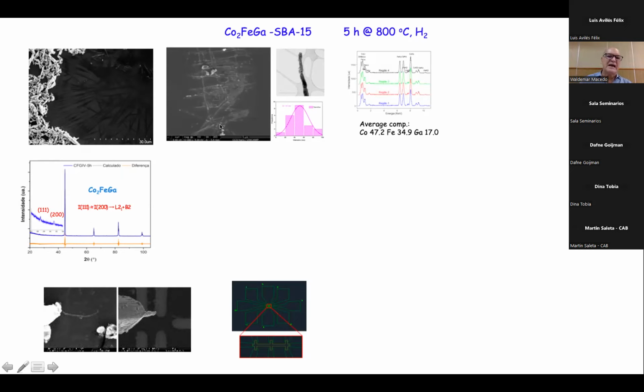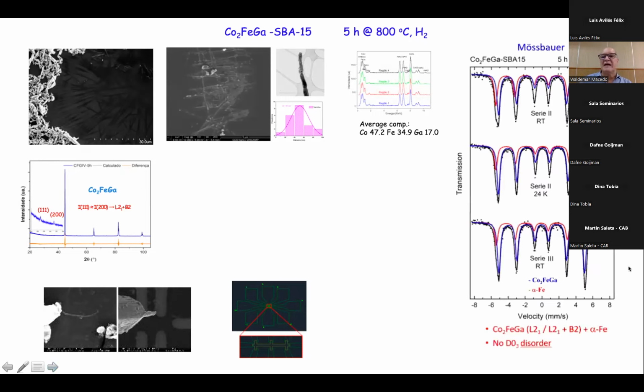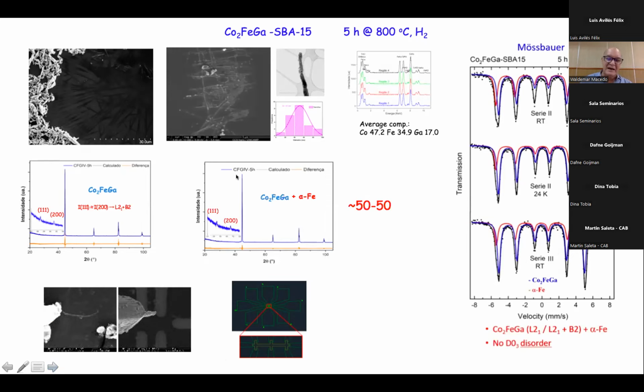Heusler alloys. Our idea was to isolate just one single nanowire to do transport measurements in this kind of electrode, prepared by lithography. But after doing the Mössbauer spectra, in fact, we realized that we have a lot of alpha iron in this material. And if you use the information gained by Mössbauer spectroscopy and redo the X-ray analysis, you will see that you get equivalent fits by considering 50-50 Co2FeGa plus alpha iron. That means it's almost impossible to separate alpha iron from this alloy phase with conventional X-ray diffraction.